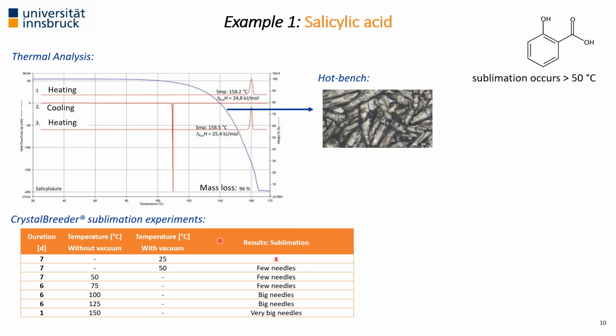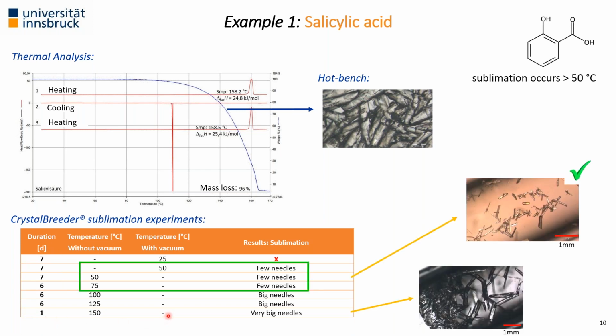So we did crystal breeder experiments. We varied the temperature and whether we used no reduced pressure or we reduced the pressure. And this gives you an idea about the duration of the experiment when we then checked and were satisfied that at least a few crystals were observed. What we learned from this example is that at higher temperatures, we have strong sublimation occurring, but the crystals do not look nice. When we decrease the temperature or potentially also reduce the pressure, we are able to grow some really nice single crystals, which can then be forwarded to standard laboratory single crystal structure analysis with the devices that are around. So this was an example where we know it works.